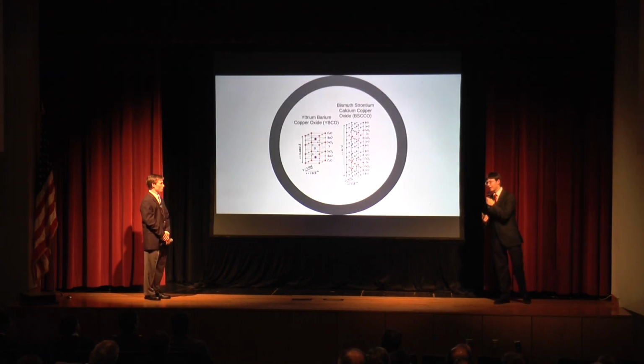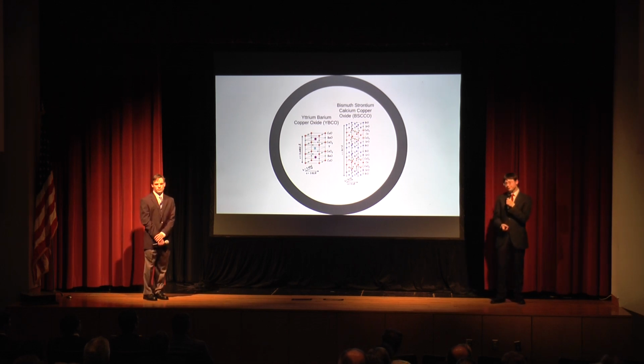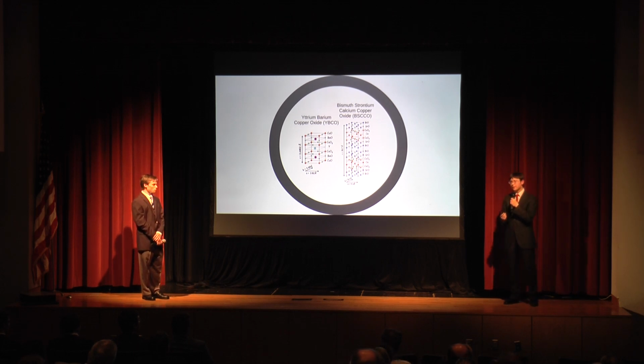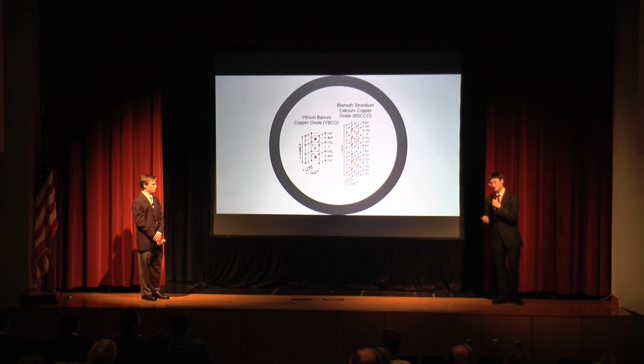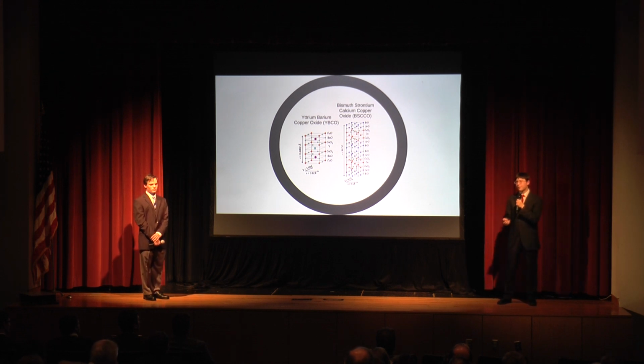And we found two very long-named materials that we wanted to look into. Yttrium-barium copper oxide, or YBCO, and bismuth strontium calcium copper oxide, or BSCCO. Now, the company American Superconductor, when they put it in those power lines, used BSCCO, because although the reagents to make the material are more expensive, the processing techniques that were in place at the time made it a more economically feasible material to make these cables out of. But we thought, because electric cables are very thick, because they need to overcome that innate resistance, with a superconducting material it can be at the nanometer scale in diameter and carry the same amount of electricity. So we looked into electrospinning YBCO.